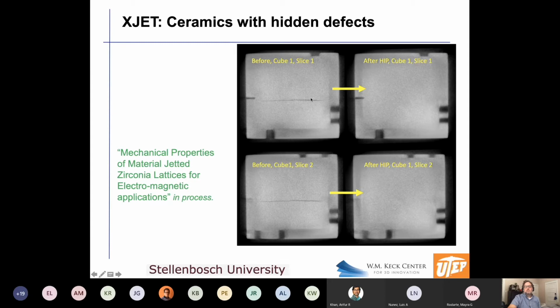But we just squeezed the poop out of it. And in the end, we got fully dense parts. Now, if you think about this also, that lattice I showed you, you could do that with that as well. And it wouldn't compress the struts together because the pressure would get into the lattice, but the actual struts themselves would get squeezed. And if there were any internal cracks there, this would fix that.